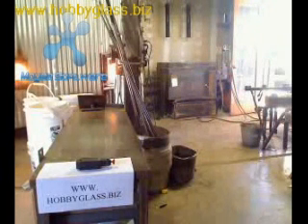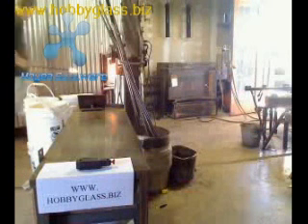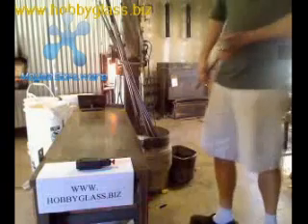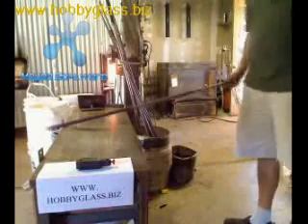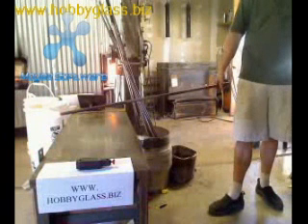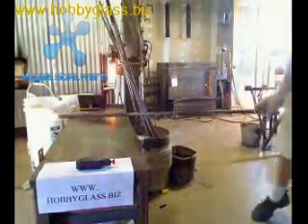The most important thing to keep in mind when you're pulling cane and murrini is that the central gather has to be an equal temperature all the way through. This is most easily achieved by working directly out of the furnace, taking a minimum number of reheats, and being conservative with the amount that you work the glass.